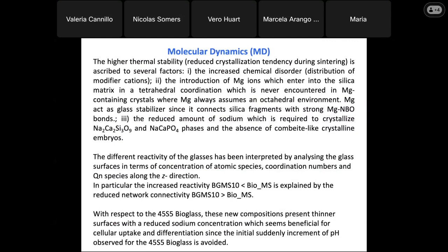And the different reactivity of the glasses was interpreted by analyzing the glass surfaces in terms of concentration of atomic species, coordination number, and Qn species. And we observed that with respect to the 45S5 glass, this new composition presented thinner surfaces with a reduced sodium concentration, which is beneficial for cellular uptake and differentiation.